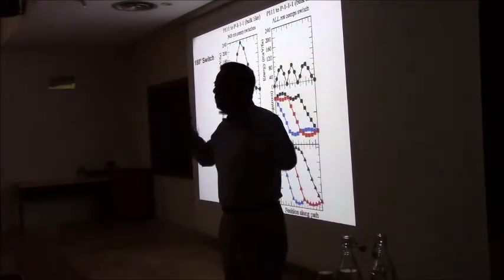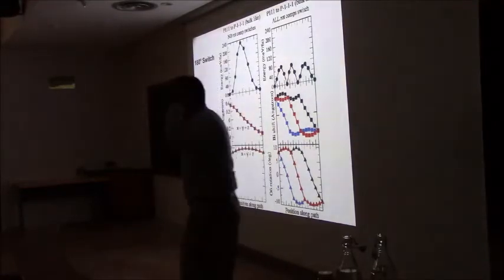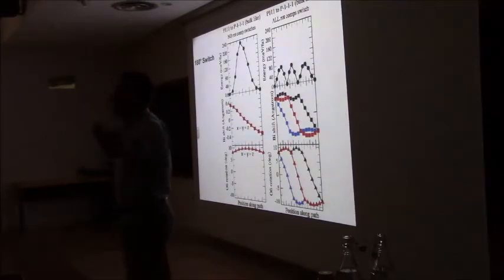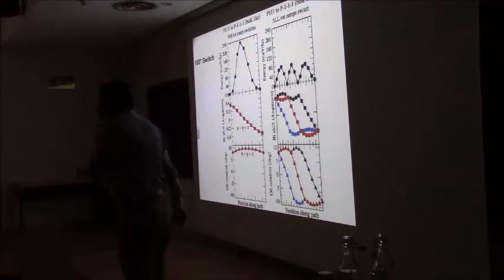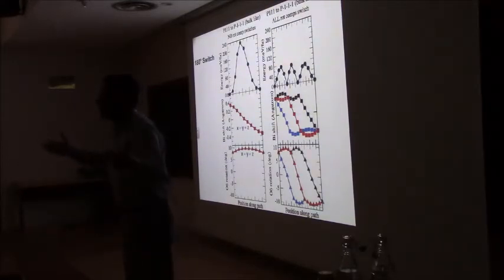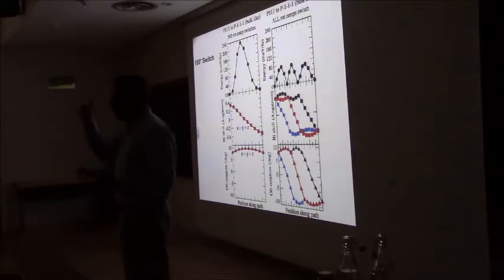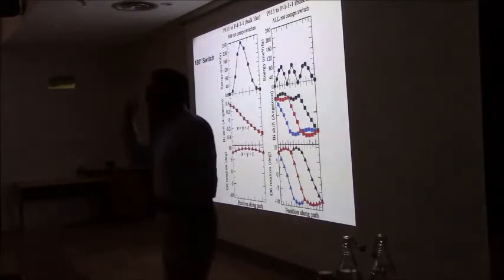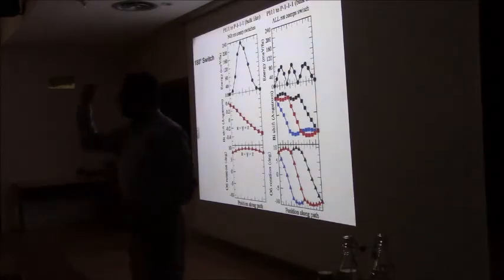And therein lies something very interesting, which I would not have believed, having been programmed to think about ferroelectrics in a certain way. The standard way of thinking about it is that the ferroelectric switch follows what is known as a Vanderbilt switching mechanism. Meaning, as I switch my polarization from this to this, it slowly reduces the magnitude of the dipole moment, and then it flips over. Unlike a ferromagnet, where I can't ostensibly change the magnitude of the ferromagnetic moment, so instead I rotate my magnetization, either a Bloch wall or a Néel wall. But bismuth ferrite was telling us, and we had seen data, that the polarization did not go through the Vanderbilt switching mechanism. Instead, it was rotating the polarization.